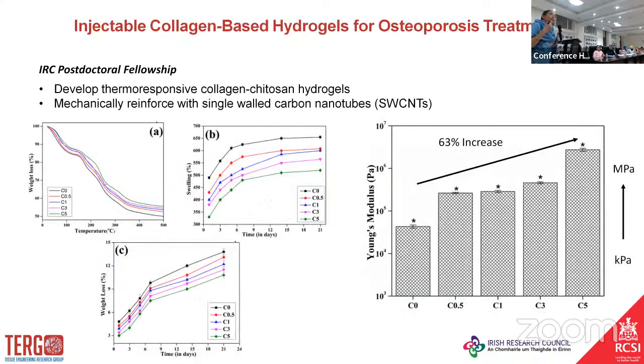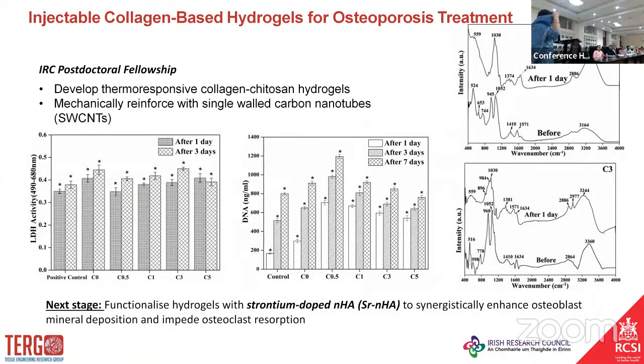Next, after preparing this thermoresponsive material, we check its weight loss and how it behaves in SBF. Most importantly, we were interested in the mechanical strength, and we found that as we add single wall carbon nanotubes into the collagen chitosan hydrogel, its Young's modulus increased by 63%, which was equivalent to human bone. So we were happy with the mechanical properties and the thermoresponsive behavior. Then we moved to the bioactivity properties in SBF, and then we checked with cells.